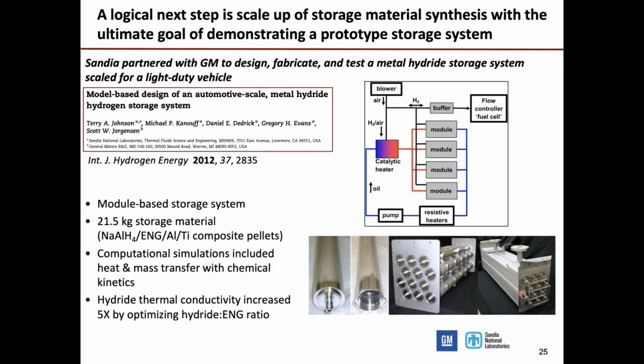Now, sort of the logical question is, well, if you're successful in this project, then what might happen? Well, we can draw a line between what we're doing right now and something that would look like a prototype tank. And Sandia has actually done this before. About a decade ago, we had a partnership with GM where they actually constructed a full-scale tank that stored hydrogen in the form of a metal hydride. In this case, it's something called sodium aluminum hydride. And they mixed it with a little bit of expanded natural graphite to improve the thermal conductivity, which is the basis of our strategy for the lithium and magnesium system.